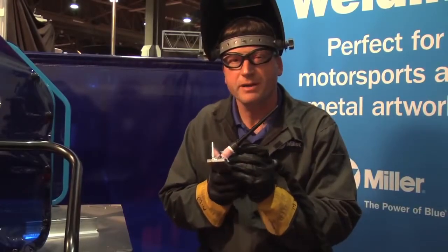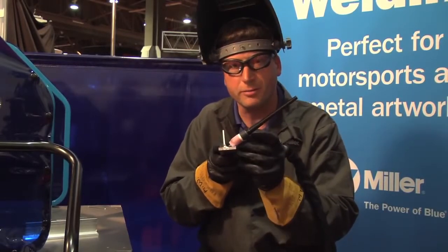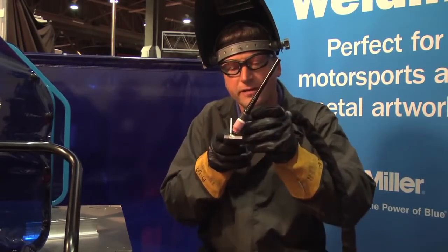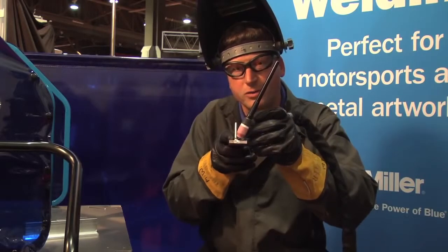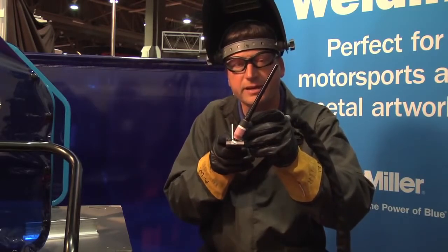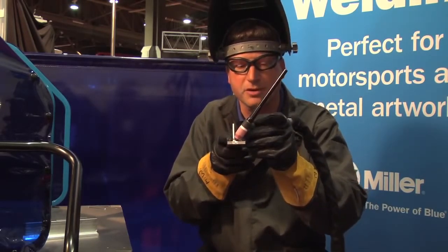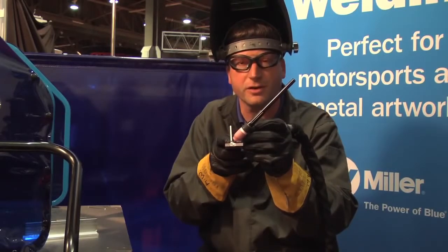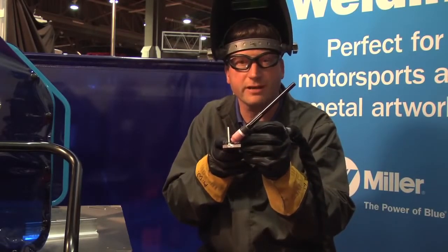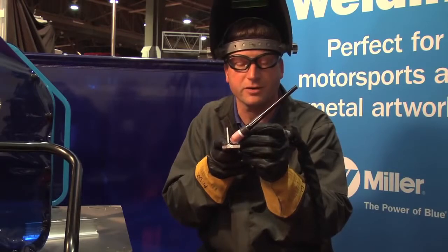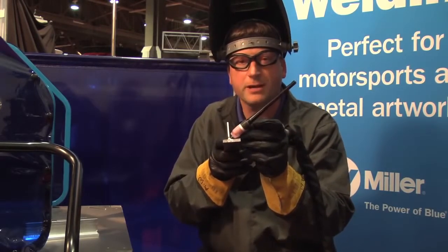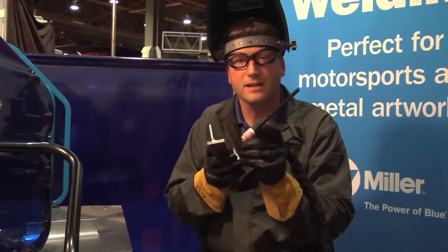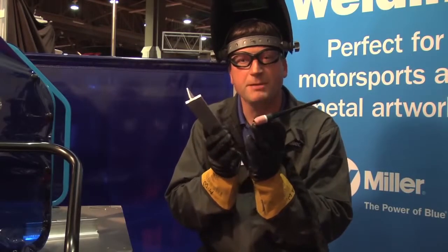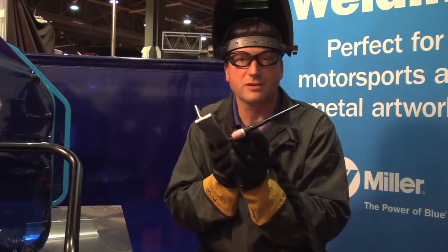So in recapping, when welding the thinner material to the thicker material, starting the arc more directed towards the thicker base metal until it gets to the proper melting temperature, and then washing it up to the thinner material will help reduce the chance of burning through the thinner material first. The wave shaping of the Dynasty allows us to tighten that up and be much more directional than a standard TIG welder would.